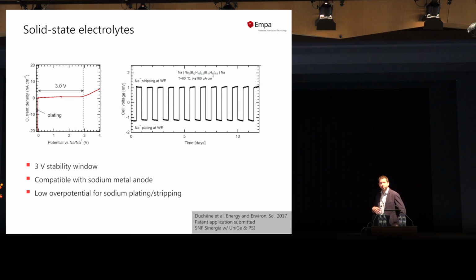So we looked at the electrochemical stability window of this electrolyte. You can see these measurements here. So we have oxidative events here above 3 volts, but below we are pretty good. You can see also these are very small currents, nanoamps per square centimeter. So it is important to look in very much detail. We don't want to do milliamps per square centimeter like people do in electrolysis. We want the opposite here. We want a stable material.